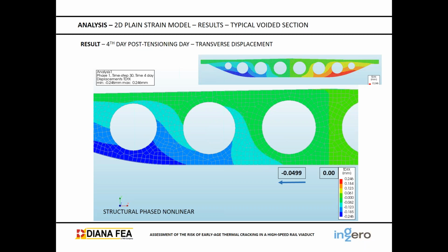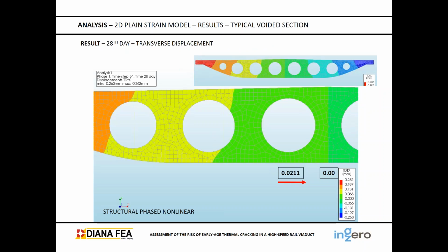Looking at the transverse displacement, we see that for the fourth day, if we look at the numbers below, under the void, it has moved zero. This is in millimeters. It's a very small movement, but we'll see after comparing with the gross section why we are looking at this. Okay, it has expanded, and on the 28th day, the transverse displacement is not expanding but compressing.